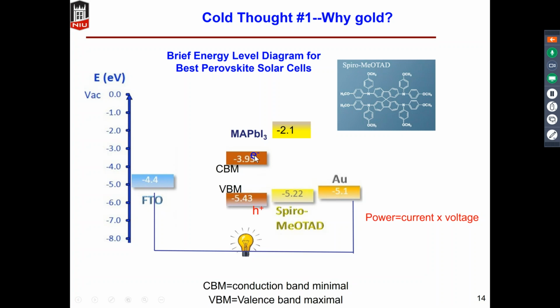And then once the electrons transport to the FTO, you don't want the electron to go back to the holes in the valence band maximum of the MAPbI3, right? So you have to have something called electron transport layer, or the so-called hole blocking layer here to block the back electron transfer. And the suitable material is titanium oxide, because its valence band is deep here, so that the electron cannot easily go back to the valence band of the MAPbI3. And its conduction band minimum is between the Fermi level of FTO and the conduction band minimum of MAPbI3. So this is the reason why we use TiO2 as the electron transport layer here.